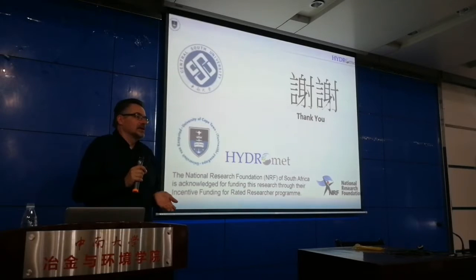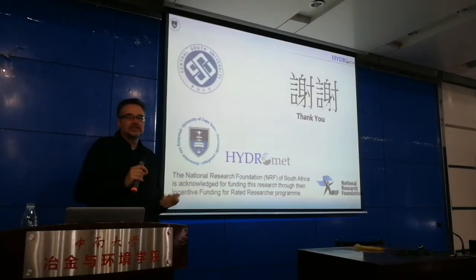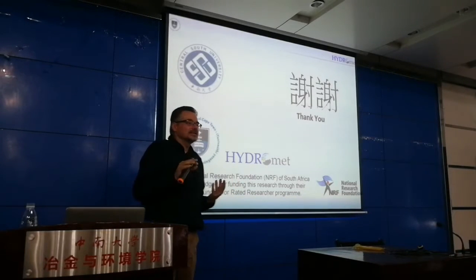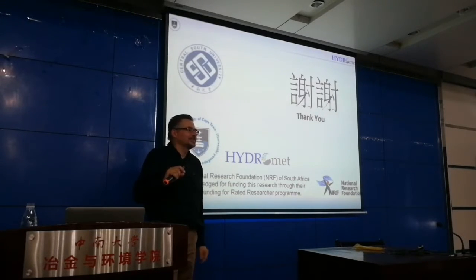I just took one look at it and I said, well, you still need oxygen because you're still oxidizing something. Yes. It's maybe not as much as you would with bioleaching, but you still need to aerate the heaps, because what you end up with is you're basically strangling the process because there's no oxygen. So there's definitely a future and an application for bioleaching, because they demonstrated that bioleaching does work. But they thought they could get away with chloride leaching, which would be cheaper. But in the end, it turned out it doesn't actually work. So now they're starting to think about using bioleaching again. So it goes in circles.